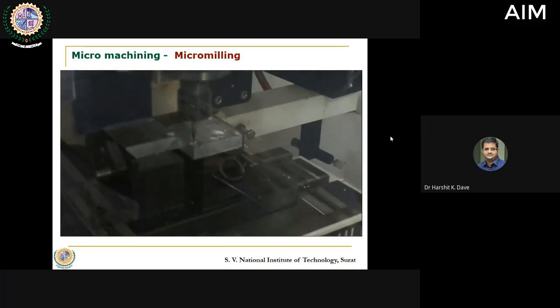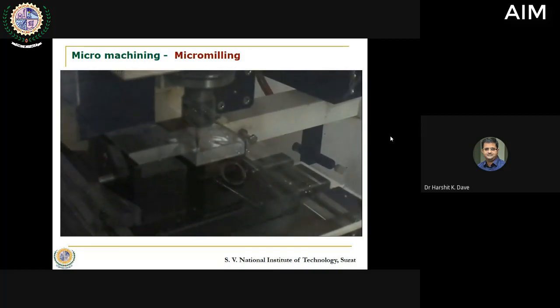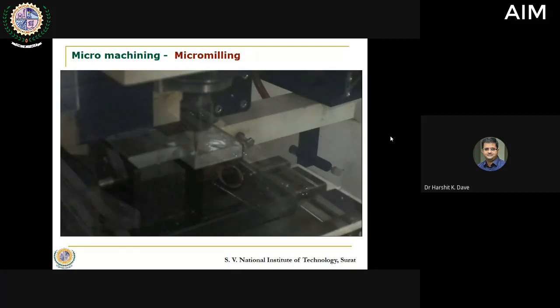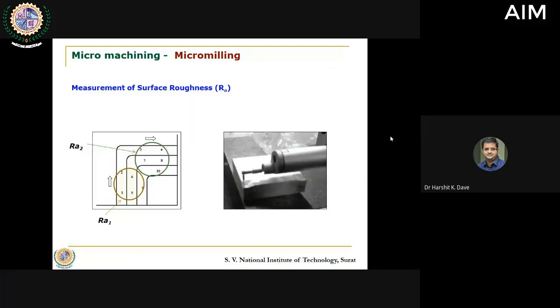Second pass is initiated. This was not that clear, but from here it might be slightly clearer. You can see that these steps are being generated. What we did was we tried to measure its dimensional accuracy and form accuracy, and then we tried to measure the surface roughness on it. Because the end mill cutter used is 1 mm in diameter, you do not have an option to reduce the width of this path. So this is remaining 1 mm.